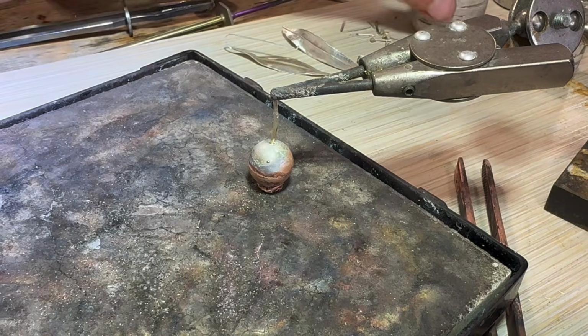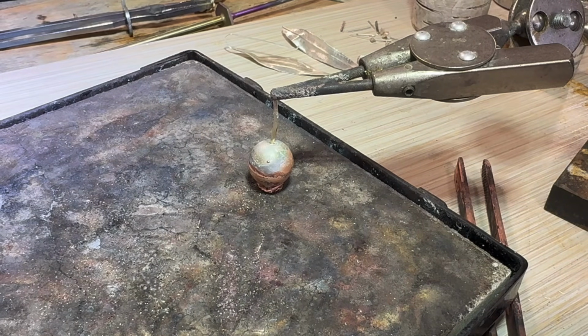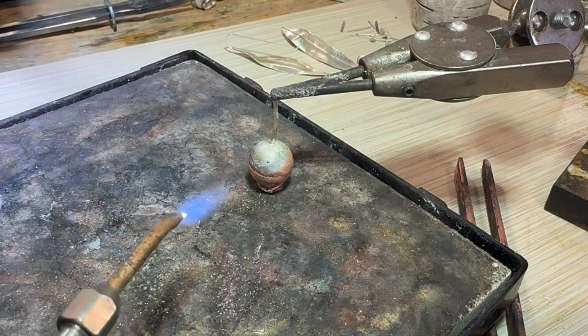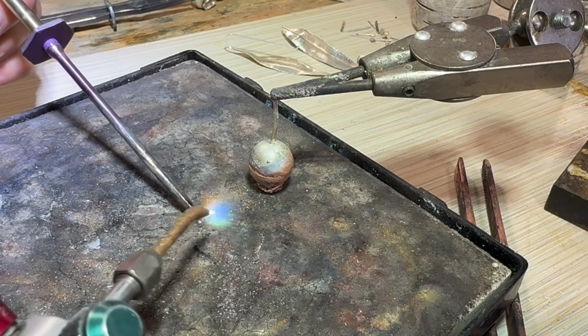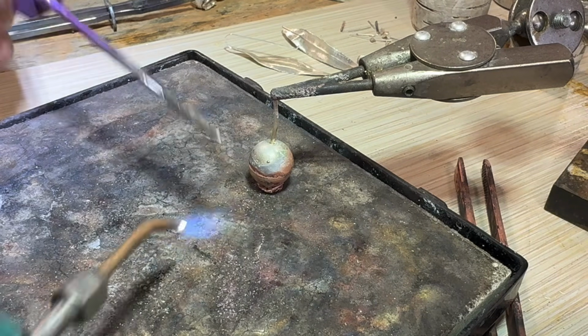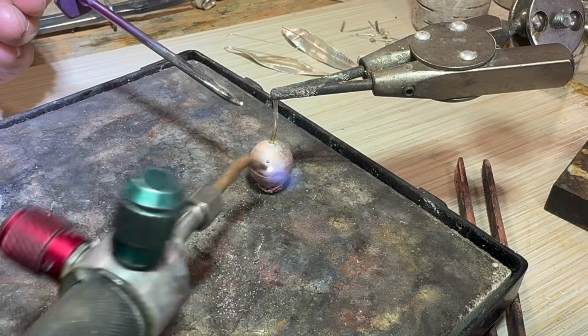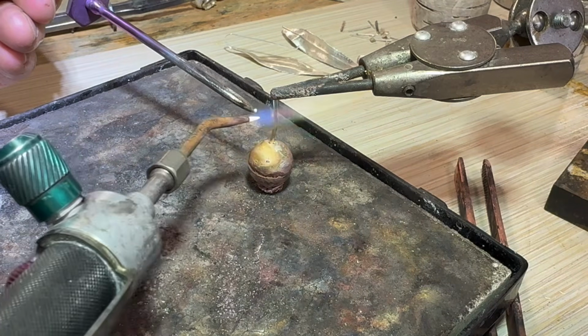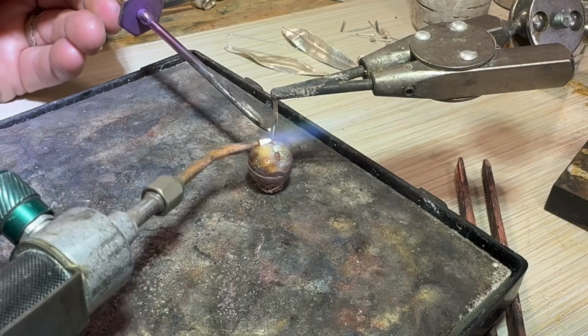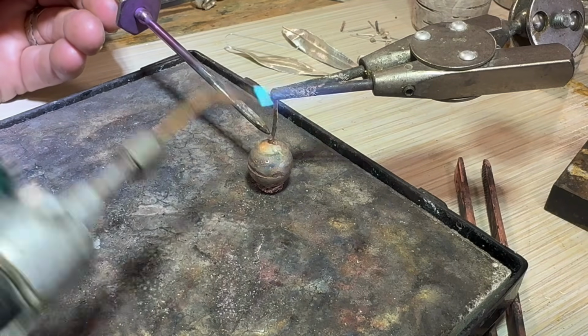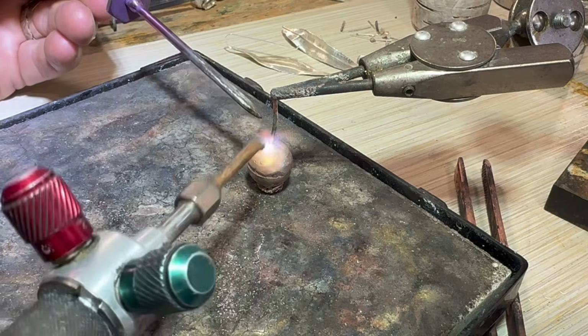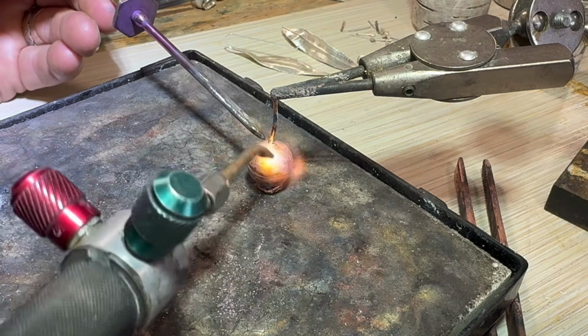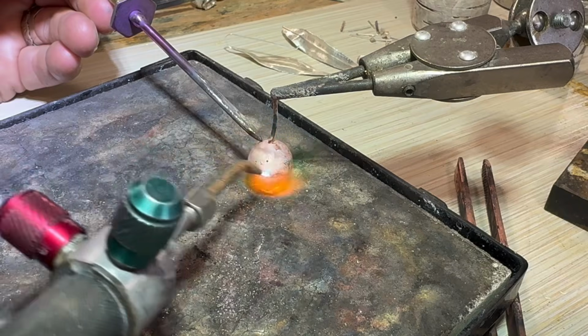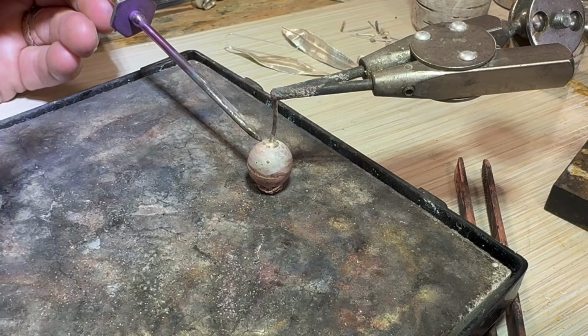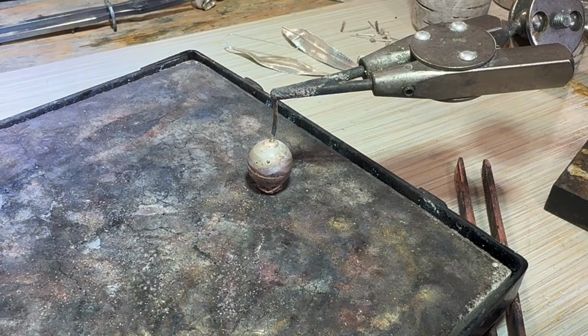So now you're going to use easy solder. And if you're paying attention to the colors on your sphere, if there's black, you might want to apply a little bit more flux. If there's yellow and white, you probably do not need to add any more flux. There's my easy solder. I'm heating the mass all the way around, barely heating that wire, mostly heating the mass. Once I see that yellow hue, I turn my torch to the side so the solder is sweat to the wire. Now I'm heating my mass to draw the solder down into the hole. And once that's complete, you have a closed hollow form.